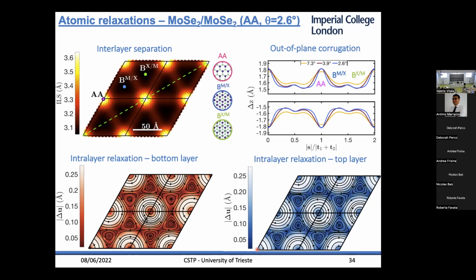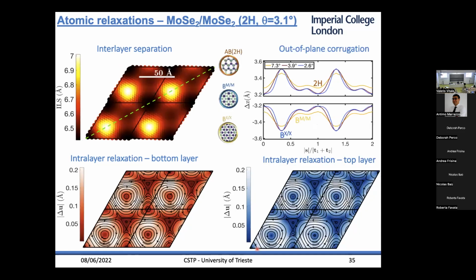Around 1 degree is still acceptable, but in twisted bilayer transition metal dichalcogenides, we don't really have to go up to 1 degree as in twisted bilayer graphene. So you can start to see these correlated states already around 4 or 5 degrees, and I'll show you why. Because the flattening of the bands happens already at 4 or 5 degrees. So for this regime, these classical force fields are quite good, at least for finding the minimum, the relaxations. We haven't studied phonons or things like that.